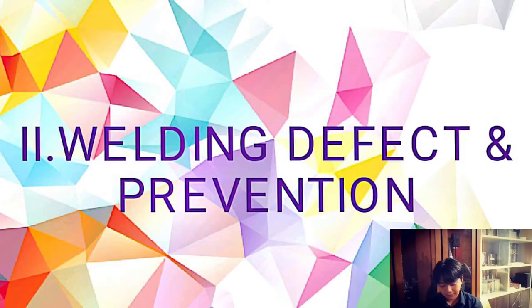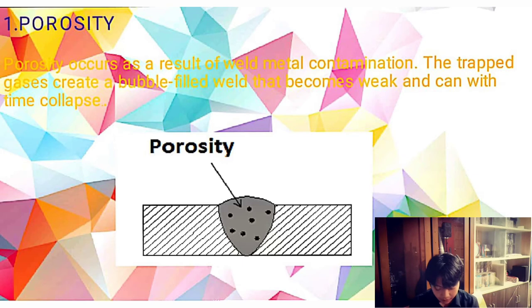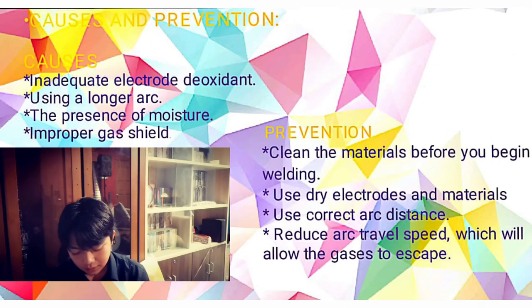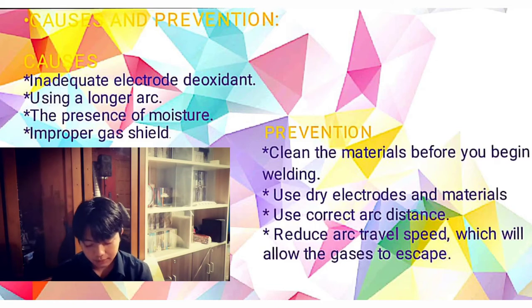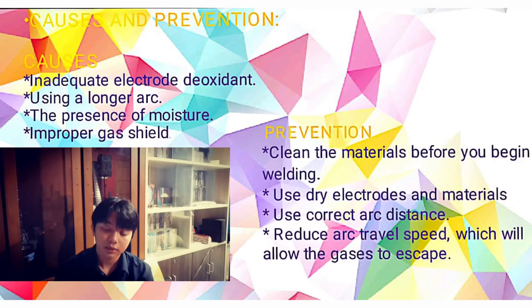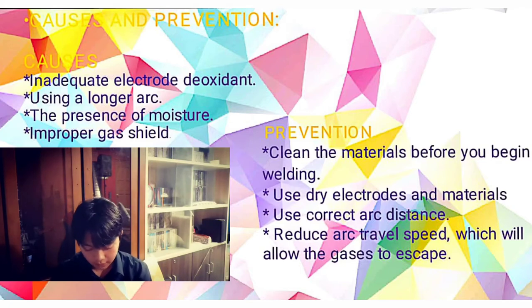Next is the welding defect and prevention. First one is porosity. Porosity occurs as a result of weld metal contamination. The trapped gases create a bubble-filled weld that becomes weak and can collapse. The causes and the prevention. Causes: inadequate electrode deoxidant, using a longer arc, the presence of moisture, improper gas shield.